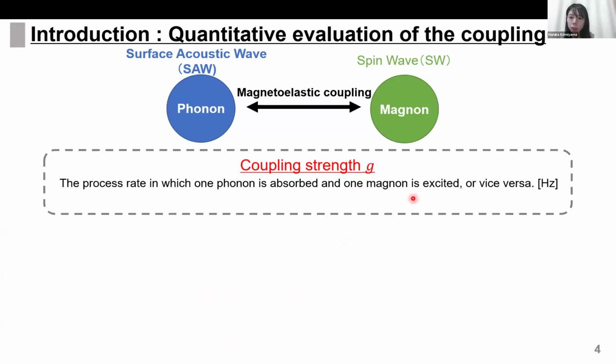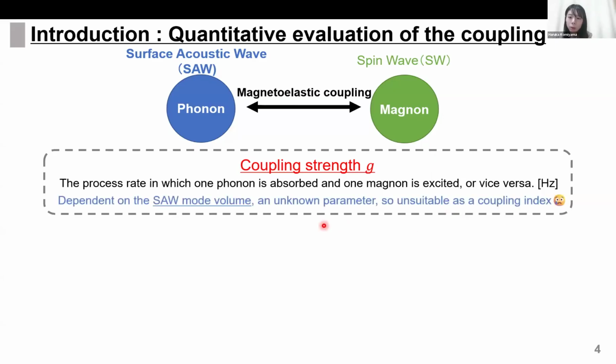The coupling strength G is commonly used as the quantitative index of the coupling. Coupling strength represents the process rate in which one phonon is absorbed and one magnon is excited, or vice versa. However, the coupling strength G depends on multiple parameters. In particular, the mode volume of surface acoustic waves is an unknown parameter that can easily vary with device geometry or material. Therefore, coupling strength is not suitable as an index for quantitatively comparing the coupling between different studies.